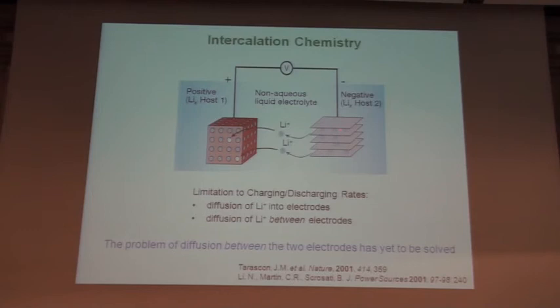They can then donate their electrons to go through a circuit to do work. They're deposited in the cathode, and then that will reduce a transition metal ion. So to maintain charge neutrality then, you have to have lithium ions migrate from the anode through some kind of an electrolyte to your cathode. It has been very well established that if you make nanostructured electrodes, you can charge and discharge your battery much more quickly because you're reducing the diffusion path through the solid, which is really the rate limiting step. The challenge, however, is in getting this high surface area electrode to be in very close proximity to the other electrode. And that problem really has not yet been solved.